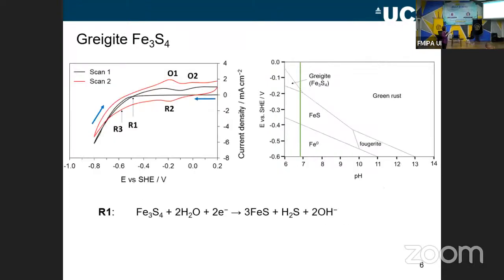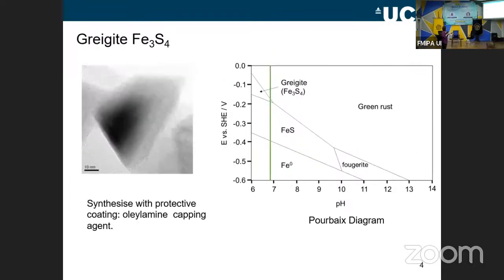So here I have what is called a Pourbaix diagram, or it's sometimes called a pH potential diagram. On my x-axis is pH, and I'm interested in the range 6 to 14. On this axis, I have my electrochemical potential, and I'm interested in the range 0 going down to minus 0.6. As you can see from the lines on this diagram, this gives us the regions where different species are stable. So it tells you what species are present at different pH and at different potentials.